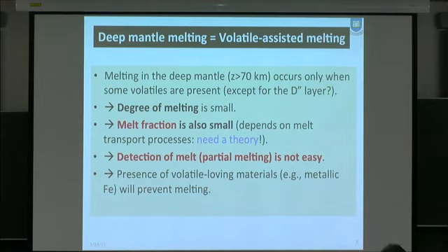So deep mantle melting, as I said earlier, is nearly impossible if there's no volatile. However, if some volatiles are present, then melting could occur. Because of this fact, the amount of melt you can create in the deep mantle is limited by the amount of volatile you have. In general, we do not know exactly how much volatiles we have in the Earth, but based on some sketchy estimates from geochemistry, the amount of volatile we expect is relatively small, like 0.1 or 0.01 weight percent. Okay? As a consequence, for any partial melting in the deep mantle, the melt fraction must be very small.